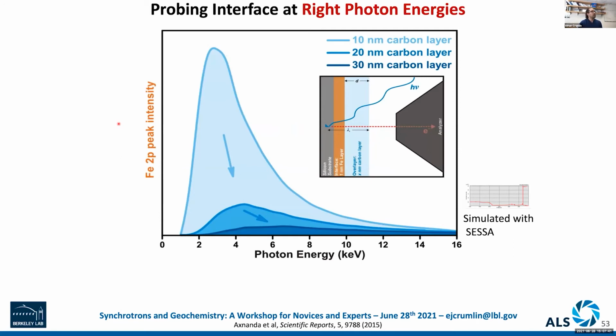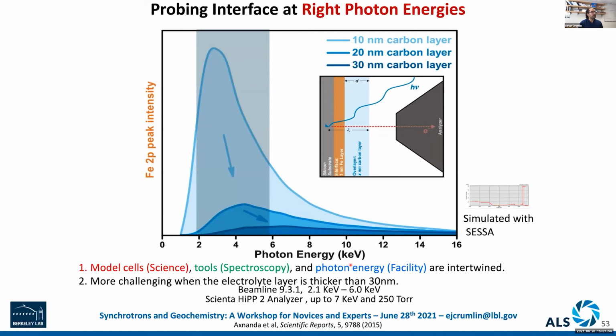And so for this, we're going to have an example where we have an overlayer of carbon, and we're going to look at a 1 nanometer iron interlayer. If we start to increase the photon energy and go into the tender regime, we see that as we go to the 2,000 to 6,000 eV, we can start to probe that iron interlayer at energies that are between the 2 to 6,000 eV. So the higher energies allow us to probe deeper.